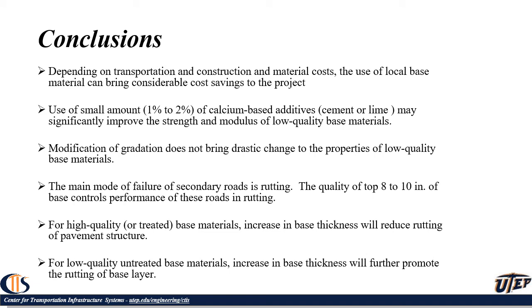Based on the lessons learned and the information I provided you over here partially, we developed a guideline, and I can give you the highlights in terms of the conclusion. The first one is, of course, obvious. Depending on the transportation, construction and material costs, the use of local base material can bring considerable cost savings to the project, especially if you can bring in a competitive environment by having several quarries in the vicinity competing on the cost. Use of a small amount, 1 or 2%, of calcium-based additives, either cement or lime, may significantly improve the strength and modulus of low-quality base materials.